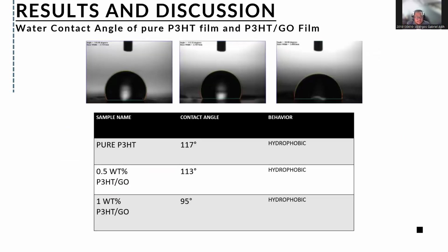Then for the pure P3HT, the water contact angle is 117 degrees. Then with 0.5% added GO, we have 113 degrees. And then 1 weight%, it is 95 degrees. So they all show behaviors of hydrophobicity, meaning they repel water on their surface. The decrease in contact angle means it becomes more hydrophilic as the GO% increases, meaning that the GO functional groups will interact with moisture and water much better.